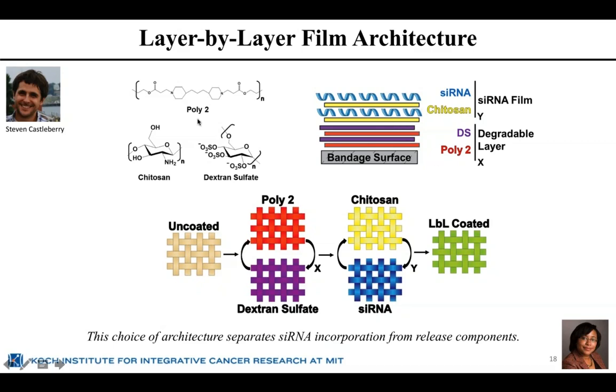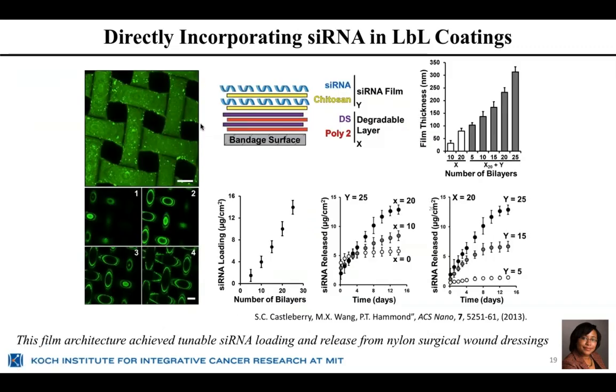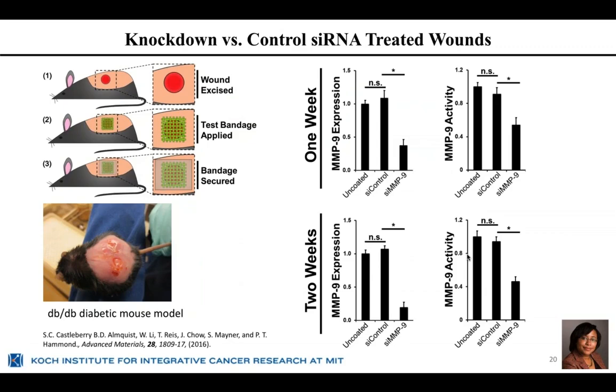The chitosan protects the siRNA for long periods of time in the wound cavity. We're able to directly coat nylon dressings using this layer by layer approach. Here you can see different loadings. We can see the linear growth of these films, and we can actually tune how much we deliver using this approach. And using a simple diabetic wound model, this is a diabetic mouse model of a wound in which we are looking at both a treated and an untreated control. We're also looking at a layer by layer film that contains a scrambled siRNA. And what we can see is that the amount of expression of this gene, MMP9, is decreased in 1 week by about 60%, and in 2 weeks by as much as 85%, indicating that over extended periods of time, this siRNA, which normally is rapidly degraded in the bloodstream, and certainly rapidly degraded in the rather low pH and high enzyme environment of the wound, is in fact sustained for extended periods of time.